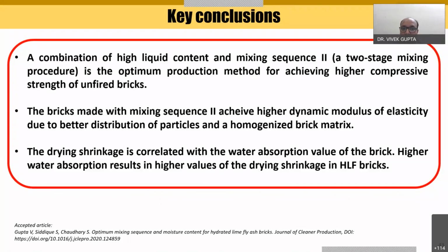The bricks made with mixing sequence two achieve the higher modulus of elasticity due to the better distribution of particles and a homogenized brick matrix. Then the drying shrinkage is closely related with the water absorption value of the brick, and higher water absorption results in higher values of drying shrinkage in HLF bricks. This particular work was related to the mixing sequence.